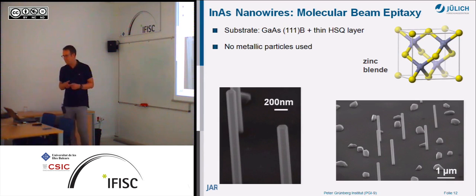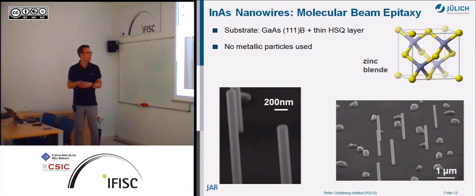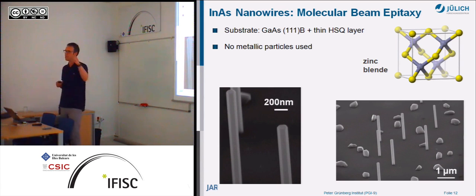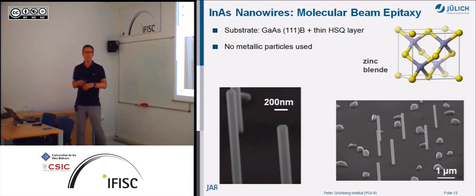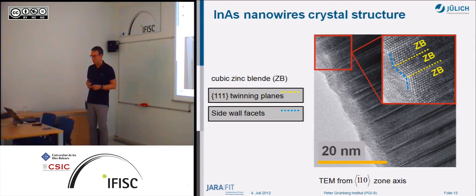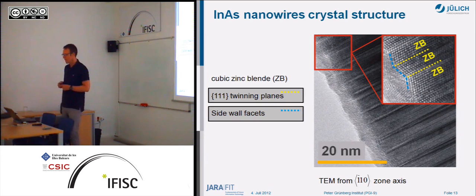We have other methods to fabricate the nanowires. It's molecular beam epitaxy, so it's not with a gas source, but in a vacuum. Here the method is slightly different. We're using a thin HSQ layer covering a GaAs wafer. And here you see the nanowires grown. The reason why they grow here is that you have some pinholes in this mask layer, and in these pinholes the nanowires grow. So this is an alternative way to grow the nanowires.